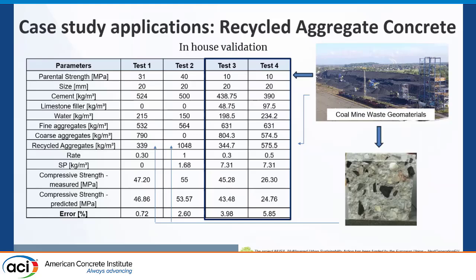It's a huge problem, especially if we are going to dismiss the coal extraction for the production of electrical energy. So what we did, we used both coal mine waste geomaterial as recycled aggregates. You can recognize this from the parental strength because these materials are very weak in compressive strength. But then we also crushed back the concrete containing these materials and used the concrete already containing recycled aggregates, we used it back as a re-recycled aggregate in a sense.